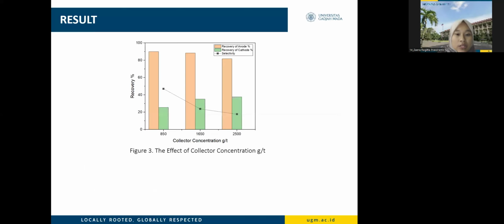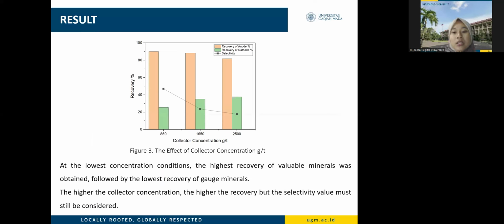Next, the result from the flotation process for collector concentration variation shows that at the lowest concentration condition, the highest recovery of valuable mineral was obtained, followed by the lowest recovery of gauge minerals. The higher the collector concentration, the higher the recovery, but the selectivity value must still be considered because the higher the collector concentration value, the more particles were adsorbed on the collector and made the particles of both the anode and cathode more hydrophobic. It can be seen from the higher recovery value, but has a lower selectivity value because there is unwanted material that is taken.